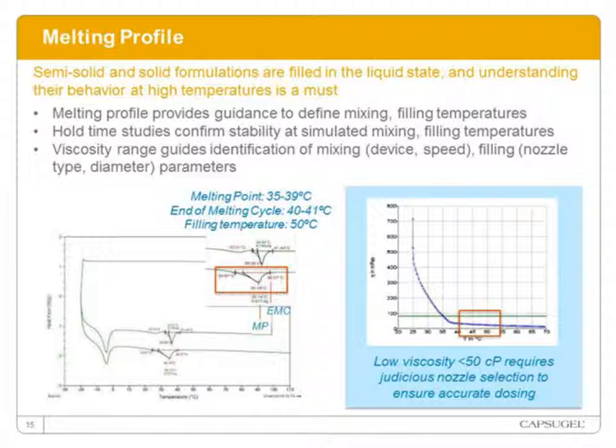Now, when conducting thermoviscosity or thermorheology measurements, we determined that the viscosity of the system was extremely low, well below 50 centipoise, and closer to the 20 to 30 centipoise range, which obviously requires careful selection of the nozzle, as key to the sealing process is actually the filling. We want to avoid having splashes during the filling, having dripping or potential bridges that could contaminate the bushes around in the capsule filling machine, as well as potentially the sealing area in the capsules.